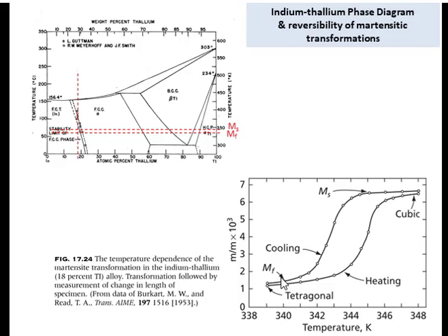In order to move the interface from one end of the specimen to the other, it was necessary to drop the temperature 5 K below the Ms temperature. During this temperature interval between Ms and Mf, the interface — or habit plane — does not move steadily and smoothly, but rather in a jerky fashion. It moves very rapidly for a short distance in the direction normal to itself, then stops until a further decrease in temperature gives it enough driving force to move forward again. This irregular motion is not apparent in dilatometer measurements but may be readily observed by watching the interface under a microscope.